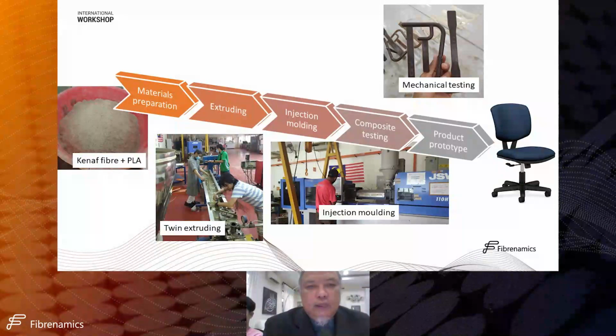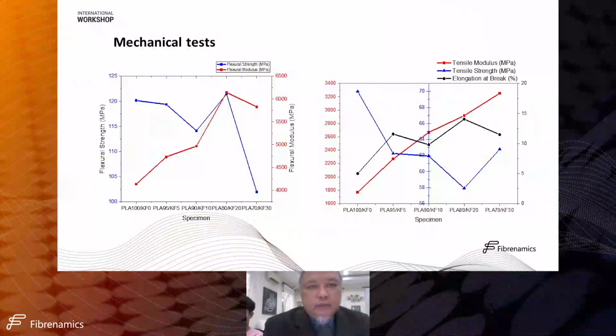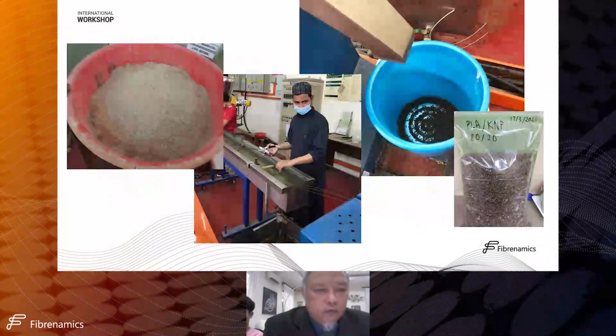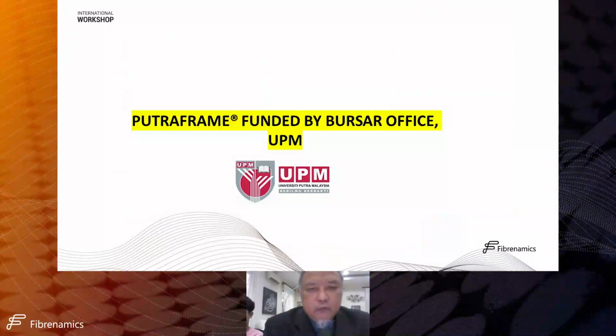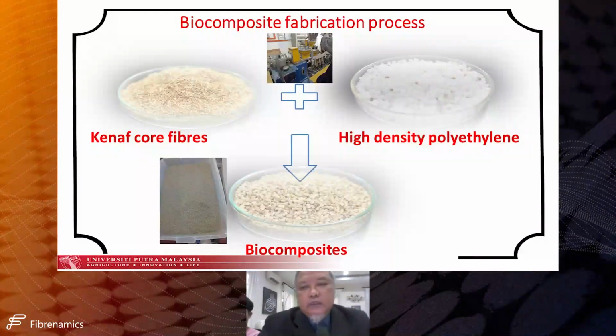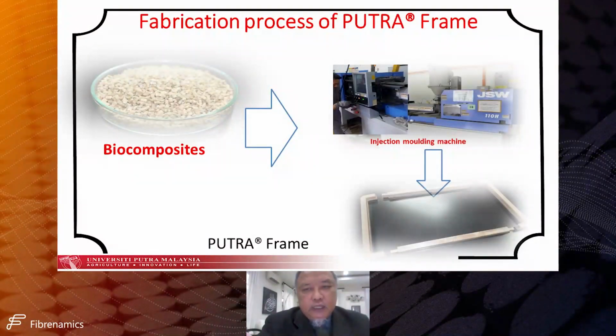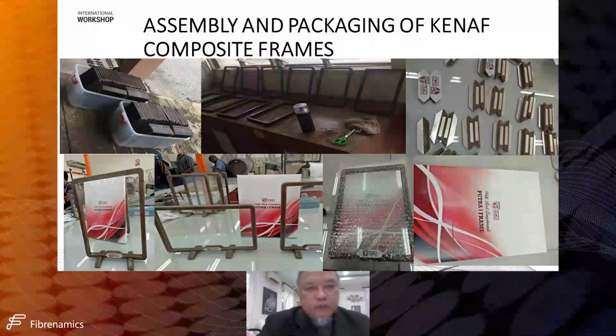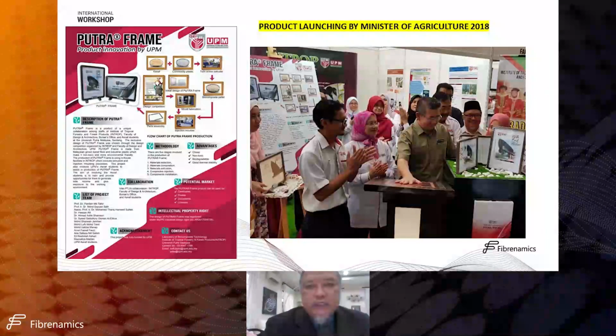And this is the process that we perform. To make the composite, we started with Kenaf core fiber. We mix it with high density polyethylene to become a biocomposite. The fabrication is quite simple using injection molding. We have the biocomposite comprising high density polyethylene, and we put it in the hopper of the injection molding machine, and we make it into the Putra frame after some assembly. This is how the assembly process took place. We also have the logo of our university there and good packaging. It was successfully commercialized and was launched in 2017-18 by our former Minister of Agriculture.